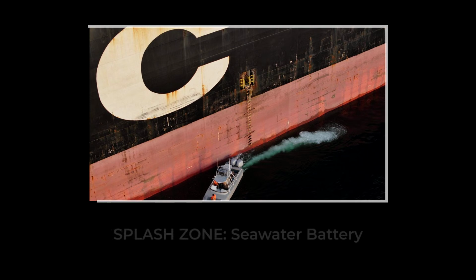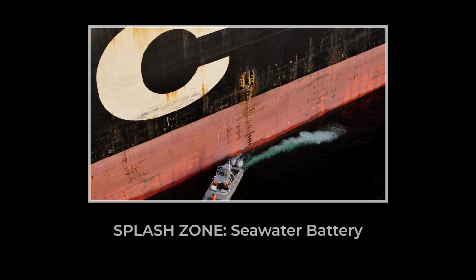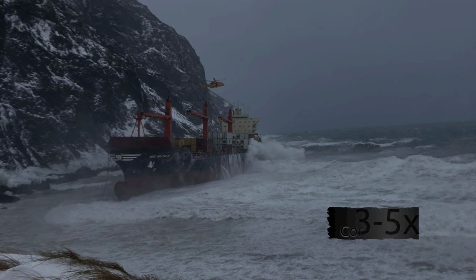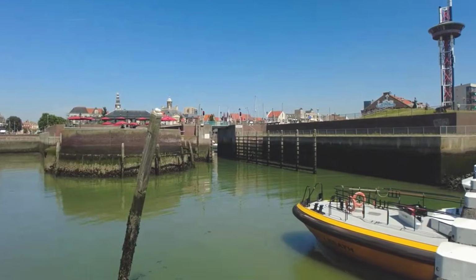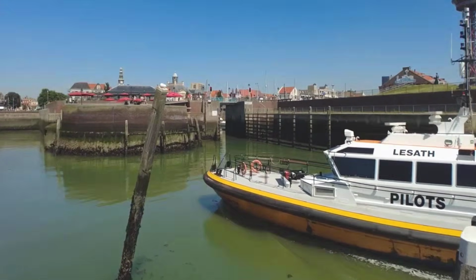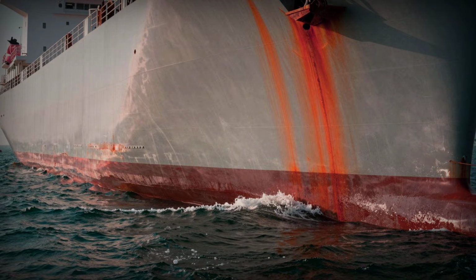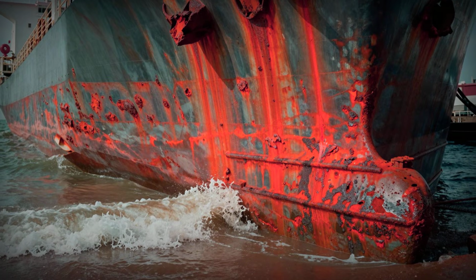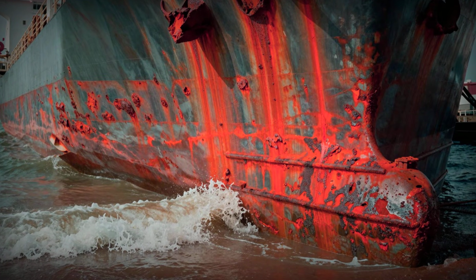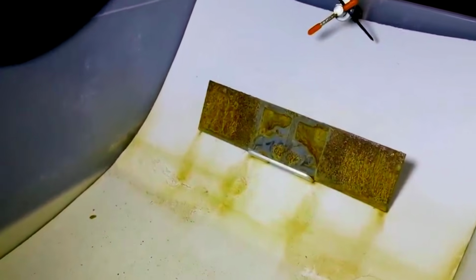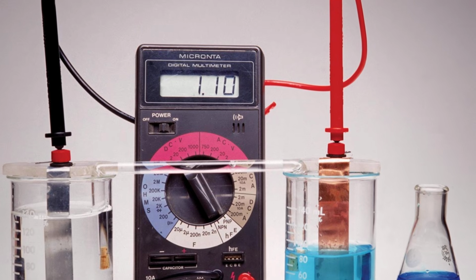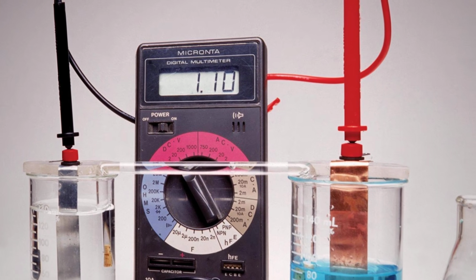In the splash zone, the area of the hull that alternates between wet and dry with every passing wave, the corrosion rate can be 3 to 5 times higher than on the fully submerged section, because oxygen is constantly reintroduced every time the wave retreats, because salt crystallizes on the surface when it dries and redissolves when the next wave hits, because that cycle never stops for the entire service life of the ship. Not magic, just electrochemistry working exactly as physics demands.